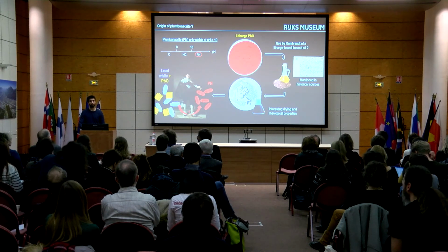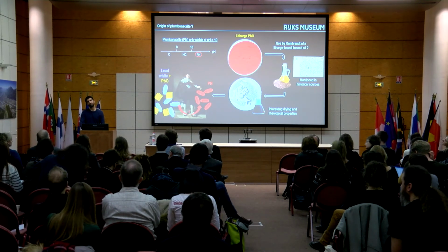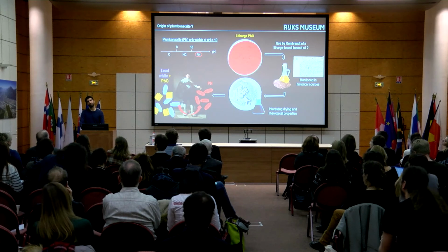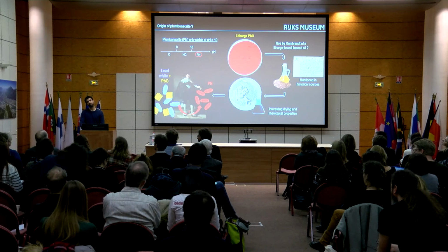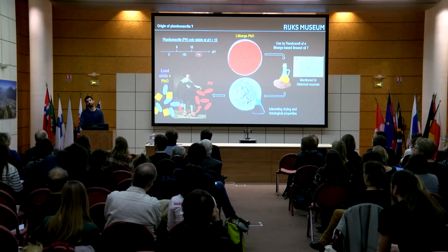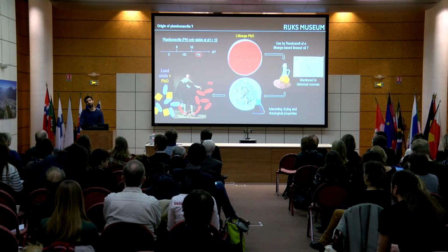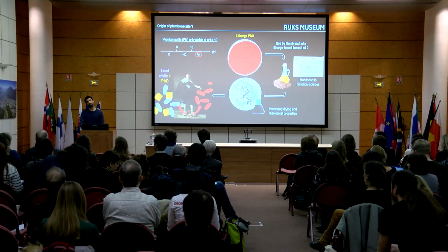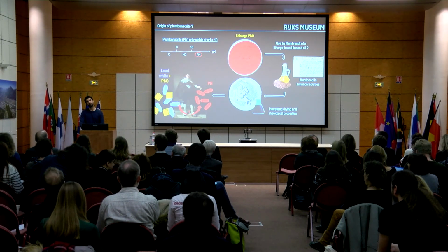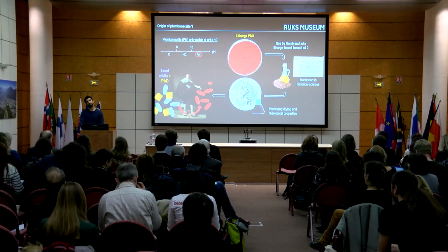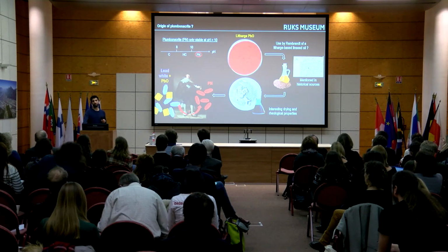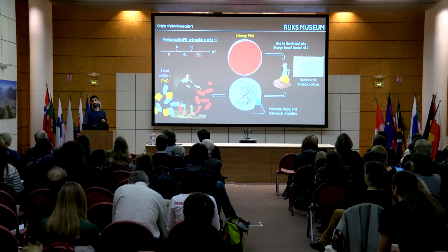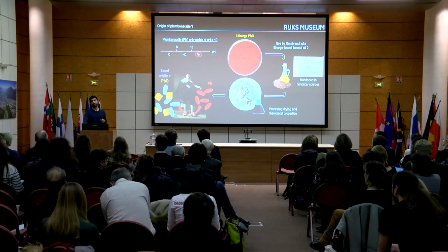One might ask the question of how the litharge was produced and whether it was a uniform phase. In Chinese art of the Song and Ming periods, we see litharge in coarse grains which have the consistency of a shell of lead oxide around a core of lead carbonate, and it affects the appearance. It gives it a brighter color, depending on the way that the litharge was produced, in that case probably by roasting incompletely. One might wonder whether the litharge used was really pure litharge.